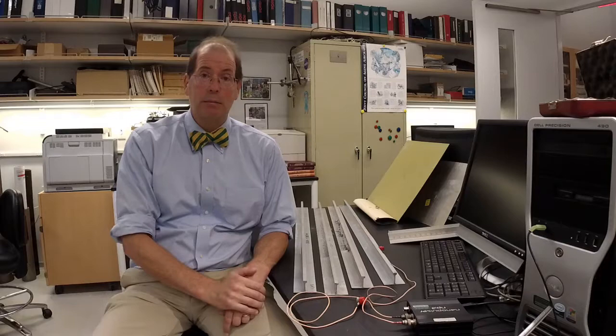Now this next one is the same, but there's a delamination, a place where the two parts of material are not in good contact. There what you might be able to see, both the reflection and transmission through the interface, but you can also see a little bit of a guided wave that's propagating along that interface. These kind of simulations are helpful to illustrate the point that you put a transducer at one location and you excite the waves that can fill the entire structure, and then at some place else you can pick up that signal and help to figure out what's going on.